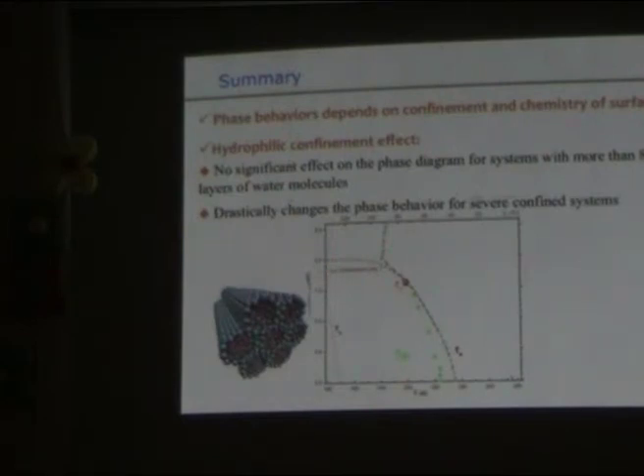So here's the summary for the second part. According to the study of this confinement, the surface chemistry and also the confinement dimensions, we know that the phase behavior definitely depends on the confinement. For hydrophobic confinement, the liquid-liquid transition is quite different from the bulk data. For the hydrophilic confinement, if the confinement is not so severe, for instance, the number of layers of liquid in the confined geometry is more than 8, then probably you are safe. But less than that, the system just changes dramatically. It doesn't look like the bulk liquid.